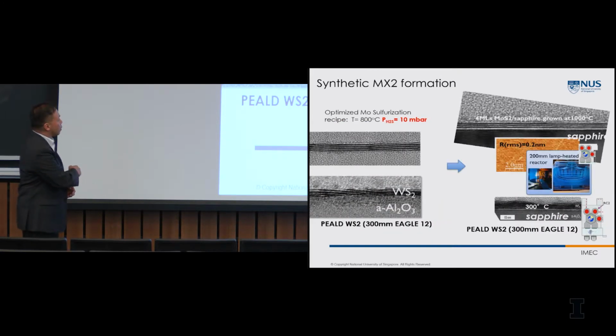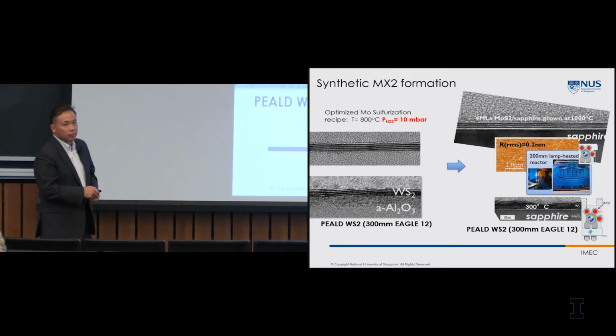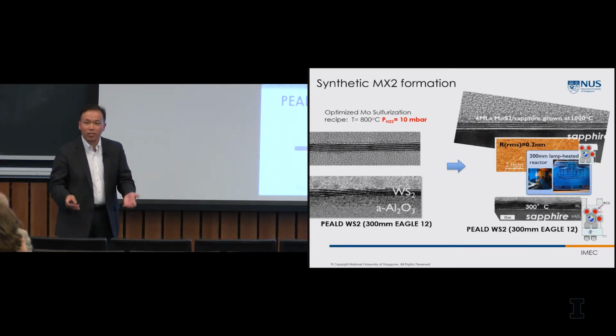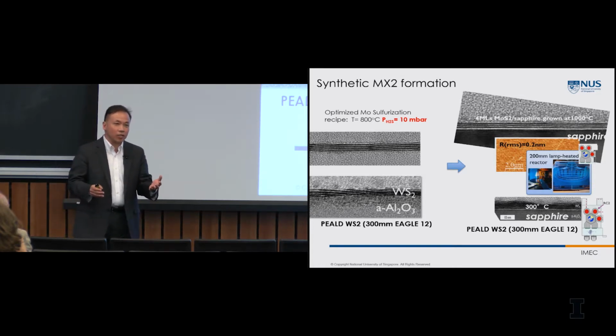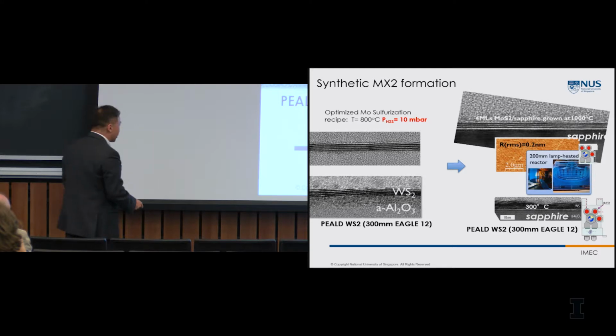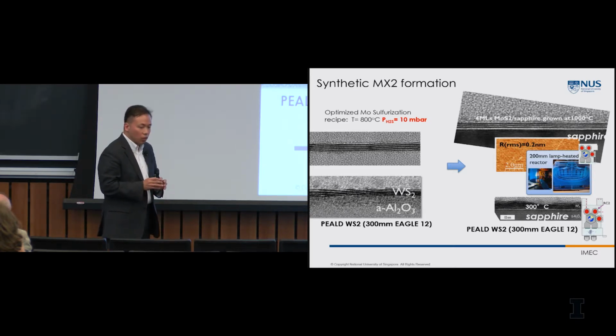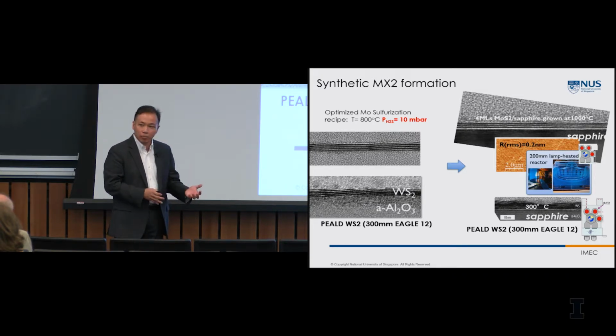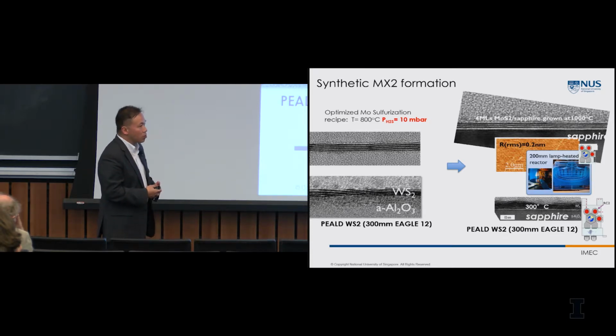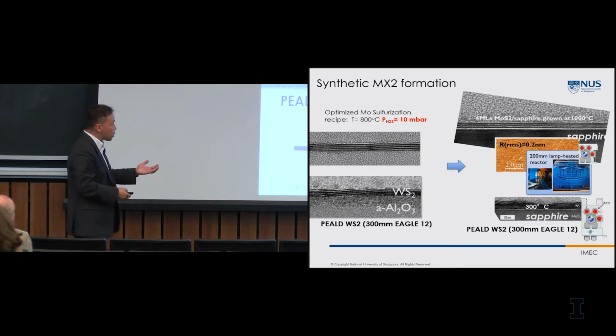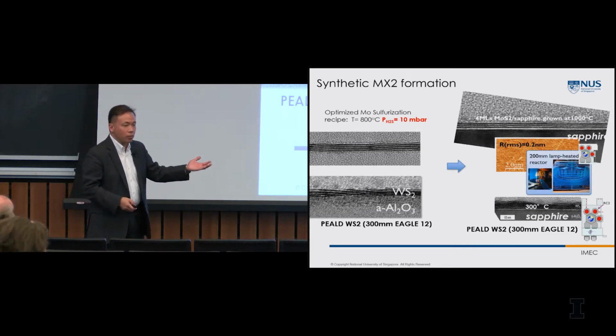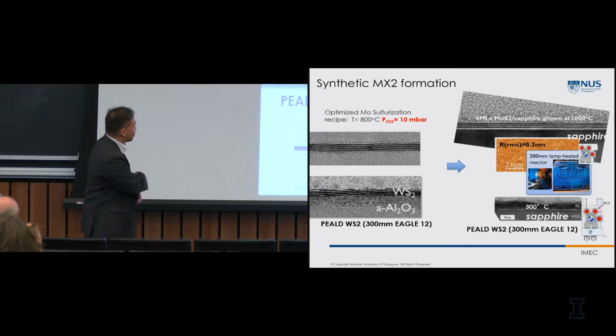Right? So previously in my group, we were looking at growing this. The problem is that they are not easy to grow at large area. So you can flake them off the native substrate, but if you want to do it on an entire wafer, it's another story. So here is work that we did, and clearly with the defects and so on, there is a lot of physics and a lot of material science that goes with it. But one of the key learnings is that they also need to be grown at high temperature, and they need to be grown on substrates that help them align in their atomic order. So that means that we have to grow them somewhere else at high temperature and transfer them in also. Okay?